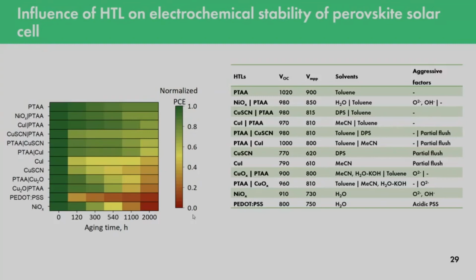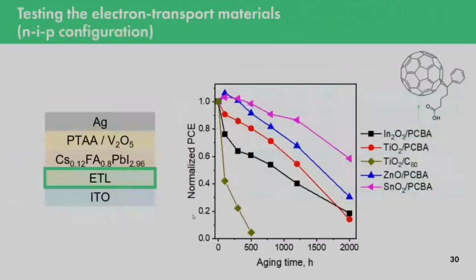So we can make a conclusion that for a stable perovskite solar cell, we first of all need charge transport materials that are chemically inert to perovskite, that won't be partially flushed by perovskite solvents, and which will give us the best starting characteristics, meaning especially open circuit voltage for the device. We also decided to check several electron transport materials, like several oxides, and also introduced C60 and the fullerene derivative PCBA between oxide and perovskite.